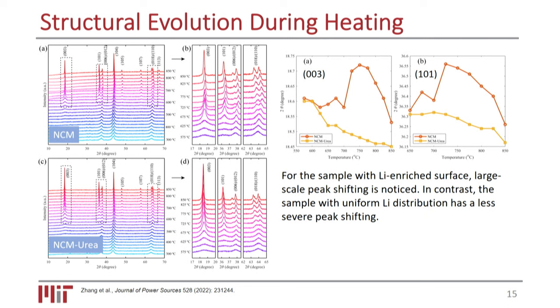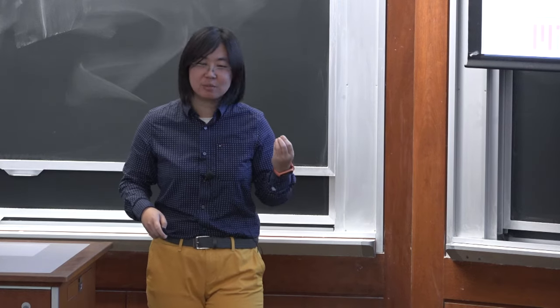But before we dive into that, I want to show you, and this is actually related to the performance, that not only do we want a good looking particle, but also a good performance. Why we can afford a relatively higher temperature but shorter calcination time is that we look into the thermal behavior as we heat up the particle. And long story short, after adding urea, our material has less shift in the peak as we increase its temperature, meaning that this new material has better thermal stability.